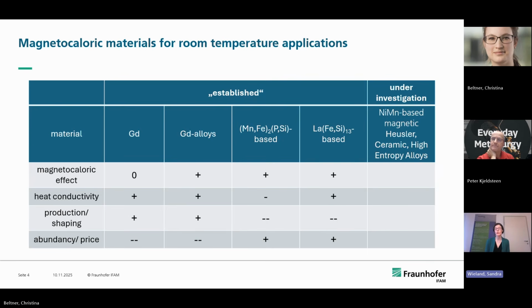After using gadolinium for quite some time, they discovered that they can use some gadolinium alloys, which have a much higher magnetocaloric effect at their Curie temperature, but it becomes spike-like. So the temperature range becomes very narrow, but the effect is much higher. This is called a first order magnetocaloric material. There you have sometimes only 1 or 2 Kelvin temperature range where the material has a very high effect. So to make a fridge which needs to work in between, let's say, 5 and 30 degrees, you need several of these materials, always one which has its Curie temperature at 5 degrees, one at 7, one at 9, and this is this cascade that you're building, always by adjusting the composition a little bit.